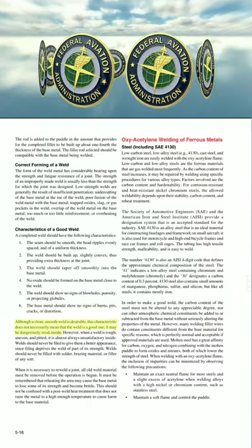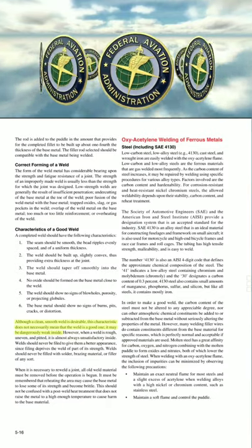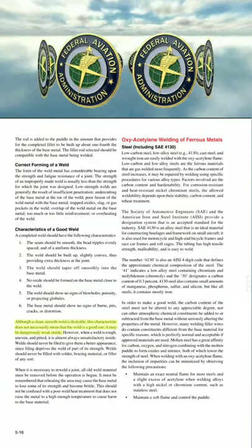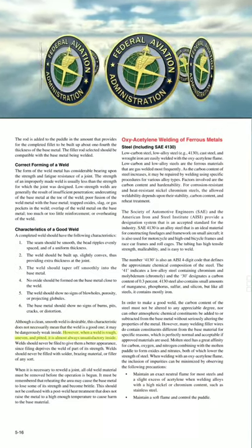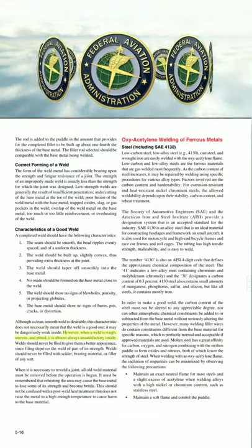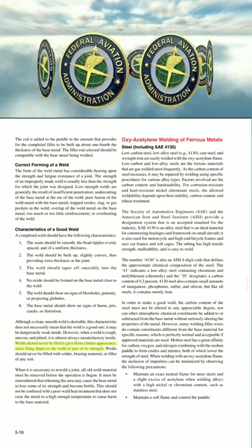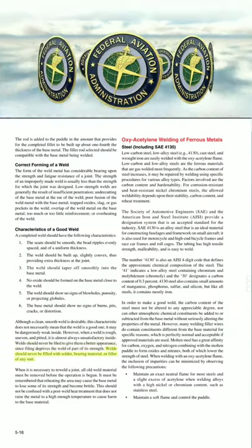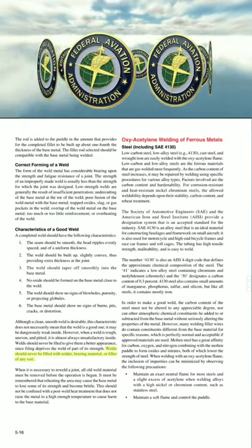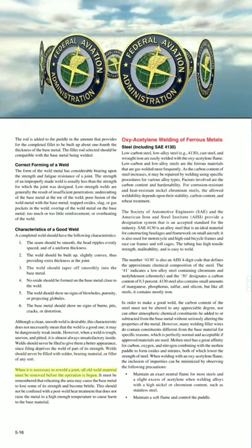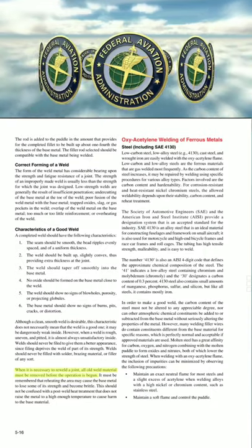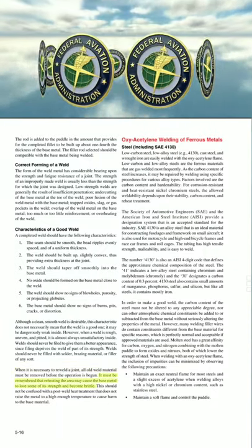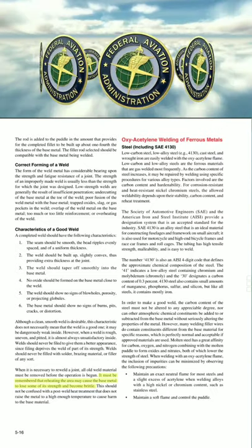Although a clean, smooth weld is desirable, this characteristic does not necessarily mean that the weld is a good one. It may be dangerously weak inside. However, when the weld is rough, uneven, and pitted, it is almost always unsatisfactory inside. Welds should never be filed to give them a better appearance, since filing deprives the weld of part of its strength. Welds should never be filled with solder, brazing material, or filler of any sort. When it is necessary to re-weld a joint, all old weld material must be removed before the operation is begun. It must be remembered that reheating the area may cause the base metal to lose some of its strength and become brittle.